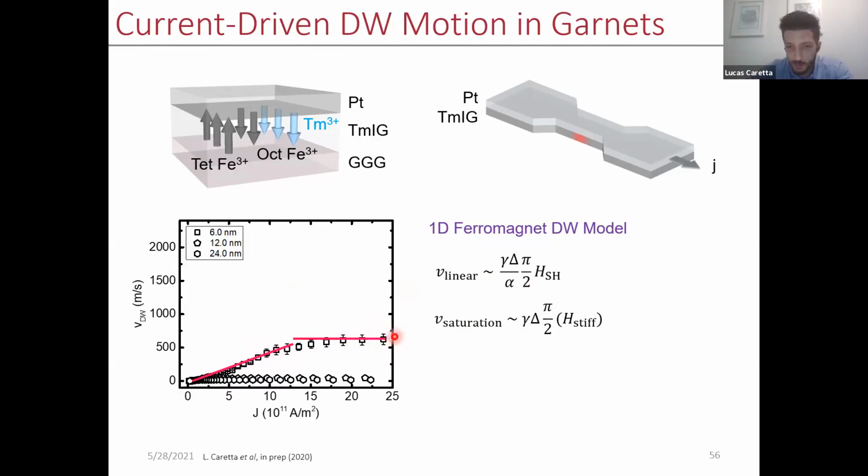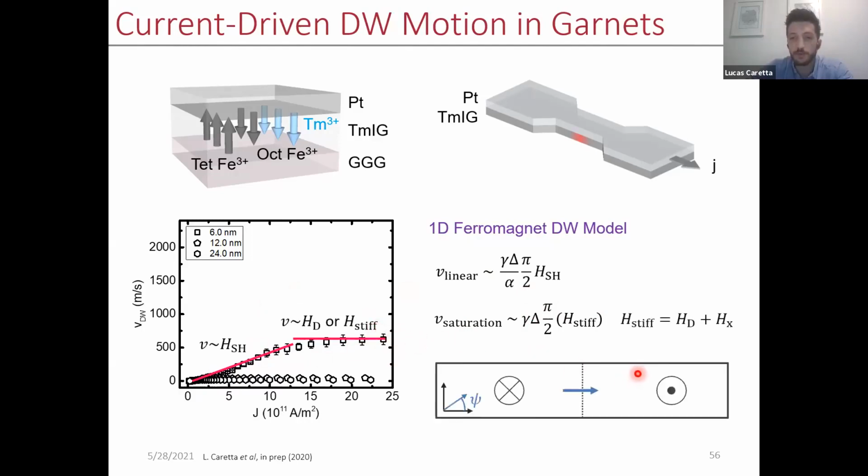And the reason that this plateau regime occurs is the following. When you torque a domain wall in a ferromagnet, not only does that current drive the domain wall into motion, it actually torques it towards a Bloch configuration as it does so. So the torque, the effective field on these material systems, is proportional to both the current and the character of the domain wall, or how Néel that domain wall is. And so as you increase the current, if you're torquing this domain wall towards a Bloch configuration, these two things effectively balance and you get a plateau in velocity.